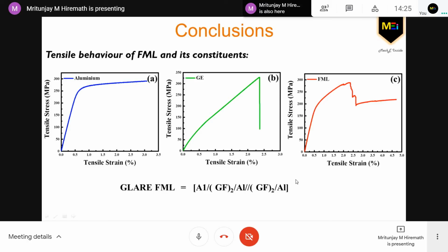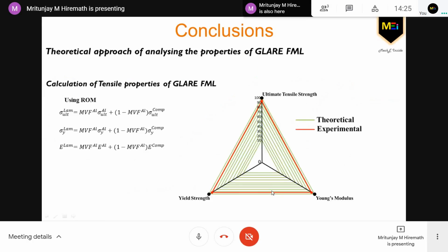And this fiber metal laminate is specifically done for this particular configuration, GLARE FML, wherein the configuration includes first the aluminium, then the 2 mat of glass fiber, then the aluminium, then the 2 mat of glass fiber, and then the aluminium. Coming back to its theoretical approach, as I mentioned earlier, it included using the rule of mixture in order to evaluate the ultimate tensile strength, yield strength, and the modulus.